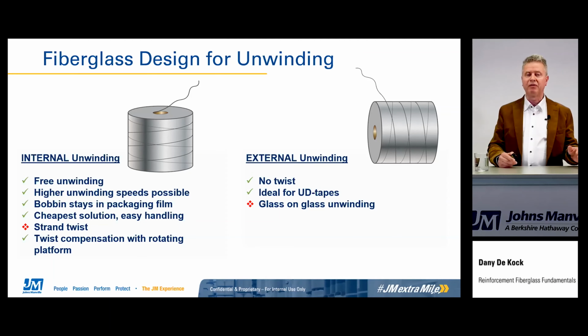And we talked about in the furnace that glass is abrasive. So when you do the unwinding glass on glass and you don't have your line set up well, you could have some damage, so that you start creating dust, or even in worst cases, fuzz from the outside unwinding. It's more complex because the creel arrangement needs to be done. So in that horizontal way, you need to position all the bobbins.